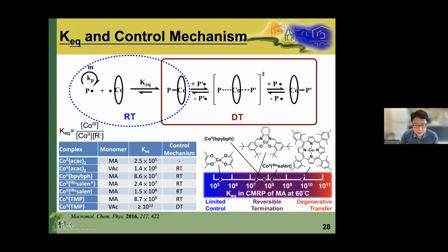and analyze the control mechanism. And we got the spectrum where we understand that when the equilibrium constant is lower than 10 to the 6, it means this equilibrium is quite small, so the cobalt-2 cannot deactivate the radical efficiently, so that the control is not good. Once the equilibrium constant is between 10 to the 6 and 10 to the 10, that means the cobalt-2 can deactivate radical to form organocobalt-3, so that they will mediate the radical polymerization via this equilibrium process. We call it the reversible termination process.